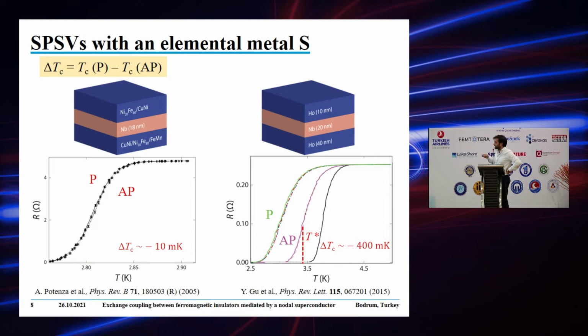So you apply a field that switches the ferromagnets antiparallel and measure R versus T. You apply another field that switches them parallel and measure R versus T. Of course, there are other effects that you have to take into account, like stray fields, suppression of superconductivity due to the applied field, and so on. But you can also work out if there is a change between parallel and antiparallel if you fix the temperature and then sweep the magnetic field. And that's what I'll show in some slides.